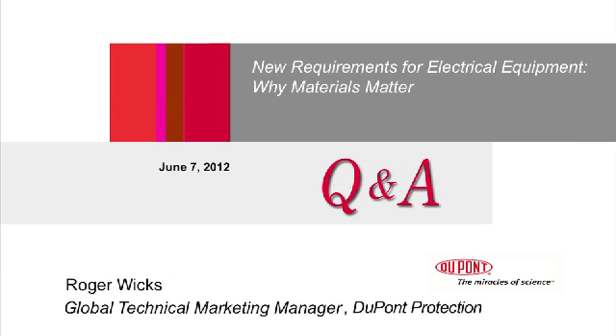Roger, another one has come through. How is the chemical compatibility of type 418 NMN? Yeah, so the chemical compatibility of the 418 NMN, and let's say that this question is related to the ATF example I gave earlier on, would unfortunately be no different than a normal NMN, because all you've done by replacing the 410 with the 418 paper is improve the resistance to partial discharge. But chemically, the 418 is similar to the 410, and unfortunately the film is no different in that situation. Where the manufacturers have had to look at chemical compatibility in these motors that have ATF, if that's the reason for the question, a film that has higher chemical compatibility is what's been necessary to withstand the effects of things like the ATF.